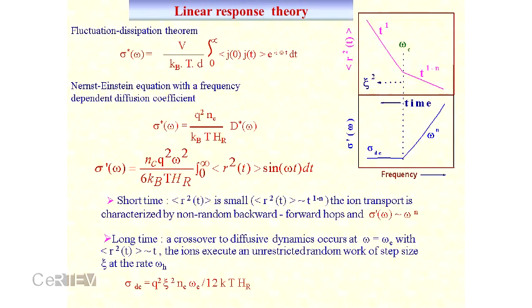The ion is characterized by non-random backward and forward hops, as a consequence of which the conductivity goes as omega to the power n, just like this in this region. But when the time is long, there is a crossover, from the dependence as t to the power 1 minus n to linear time dependence. In this region, after the crossover, the ions can execute an unrestricted motion of random steps, and finally the conductivity becomes independent of frequency, expressed by this relation.